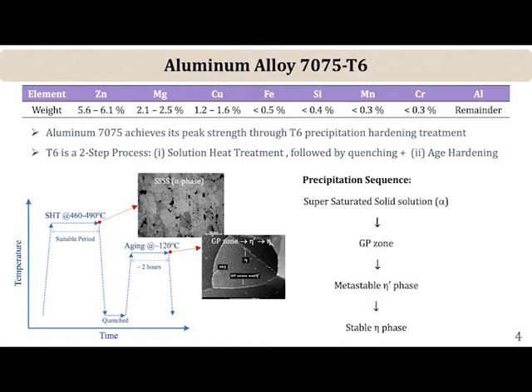However, most aluminum alloys, apart from this very fine precipitation that you get, you also have large intermetallics, typically copper-rich aluminum, copper iron-rich particles. And those are a huge problem in aluminum alloys, not just from the standpoint of limiting fatigue life, but also in terms of corrosion resistance, because there is a galvanic coupling relative to the aluminum matrix. So these tend to be somewhat nobler. So the areas around these precipitates typically tend to get attacked. And that's where pitting typically initiates.